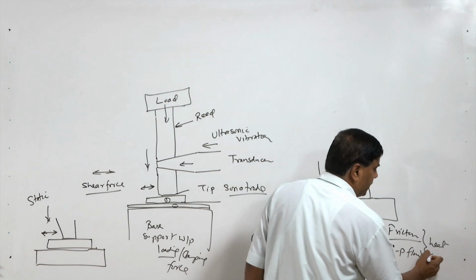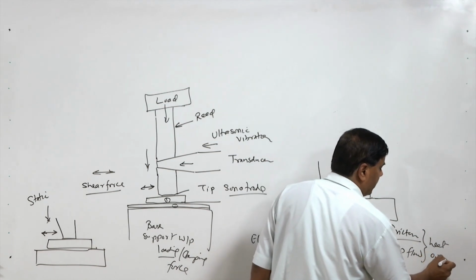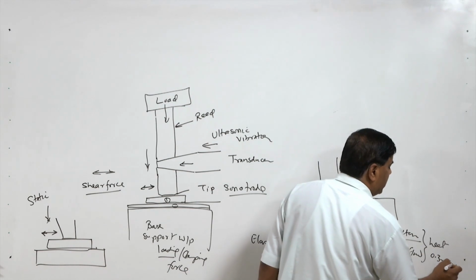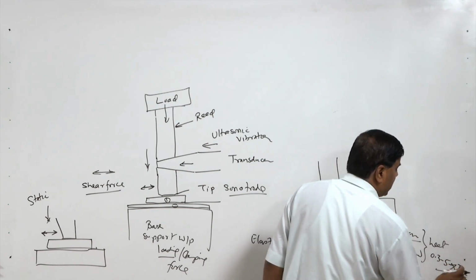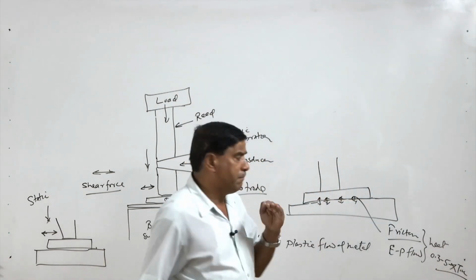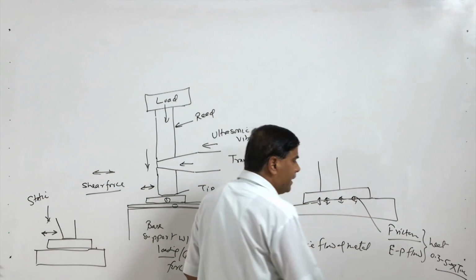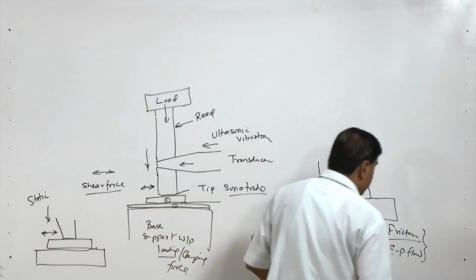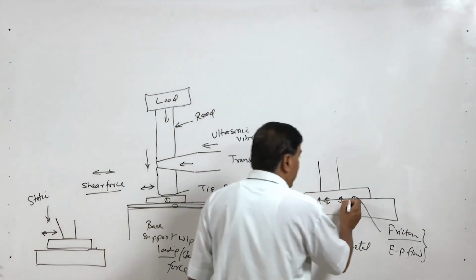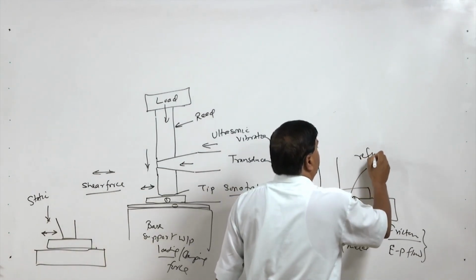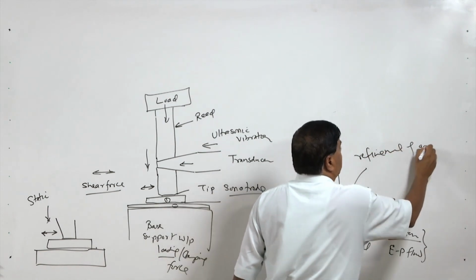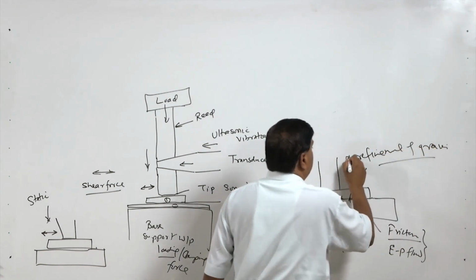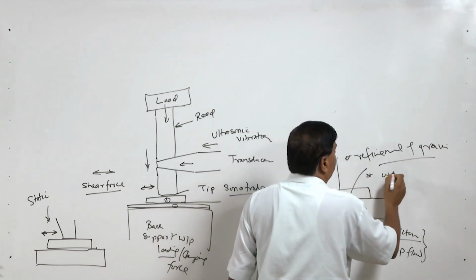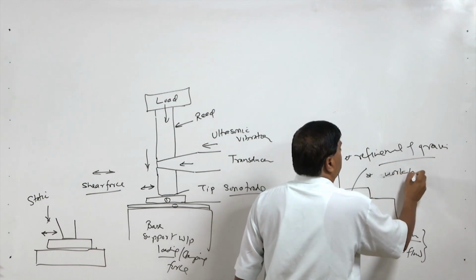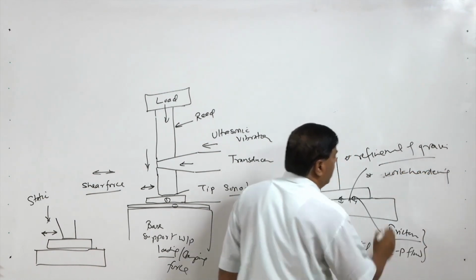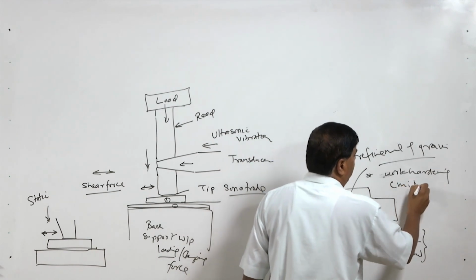So, heat generation will cause a temperature rise of 0.3 to 0.5 times the melting point of the metal in Kelvin. This increase in temperature is high enough to cause recrystallization and the formation of new grains, and these things facilitate the refinement of the grains at the interface. The second is cold or work hardening due to the plastic flow of the metal. Work hardening, although this is very mild or moderate.